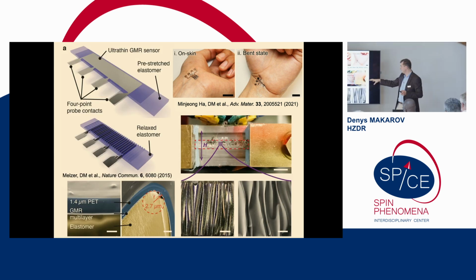What is interesting here is that when you think about such large area applications, when you put something on skin, psychologically you believe that it's super easy and there is nothing special there. But if you start thinking about it, actually there are a lot of very interesting aspects. If you do such a motion, your skin stretches 100% biaxially, okay? So basically the biaxial stretchability of your skin in this simple motion is 100%. It's very difficult to study on skin, by the way, but you can do it on a polymer: basically you use a viscoelastic polymer, put your sensor on top of it, and let it wrinkle, okay?